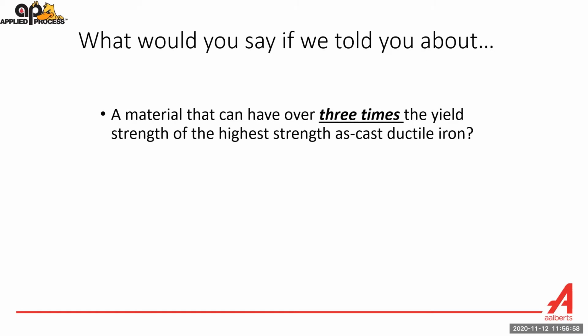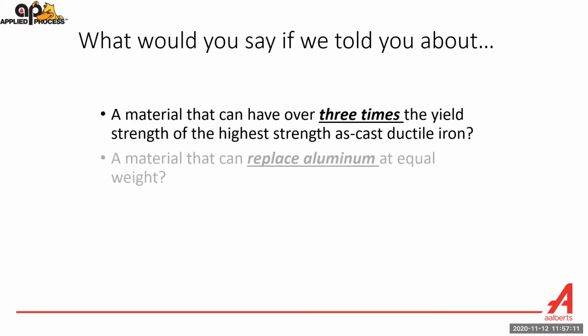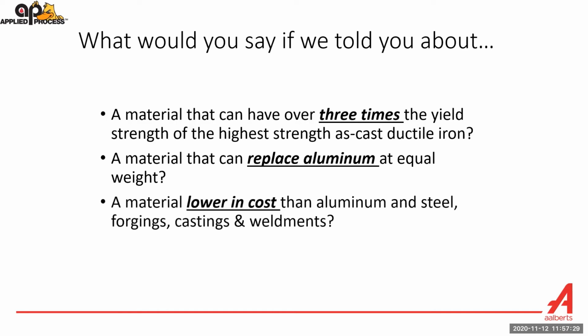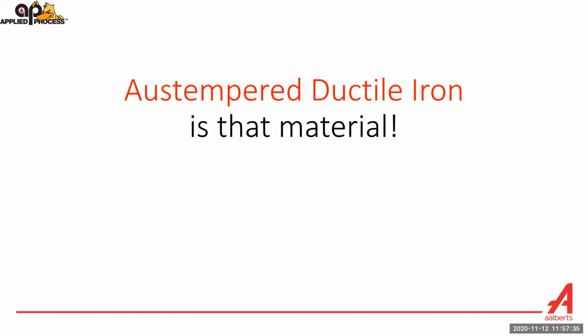So, this material can have three times the yield strength of as-cast ductile iron. So you can take an engineering material that has fairly good mechanical properties and dramatically improve them through heat treatment. And there are examples, I can't show them here or share them, but we have replaced aluminum components at equal weight. And that is huge because you're dramatically improving the strength of the material, now you can take mass out of the component. And a material that's lower in cost than aluminum, steel, forgings, castings, and weldments. ADI is that material.